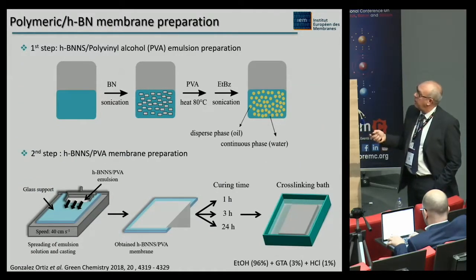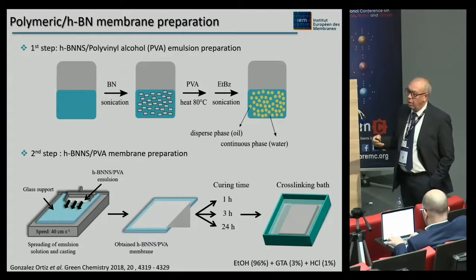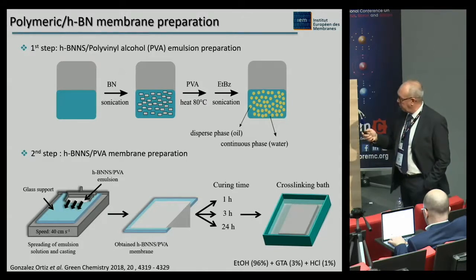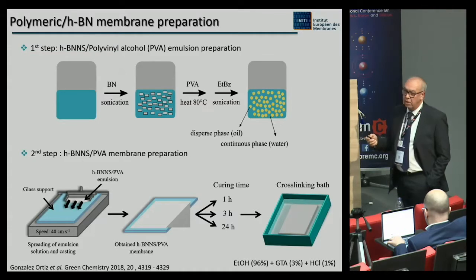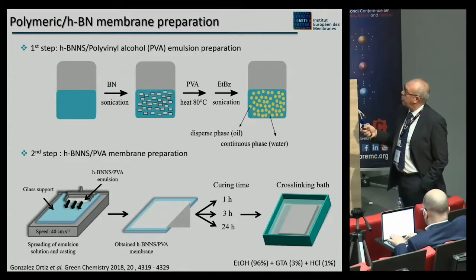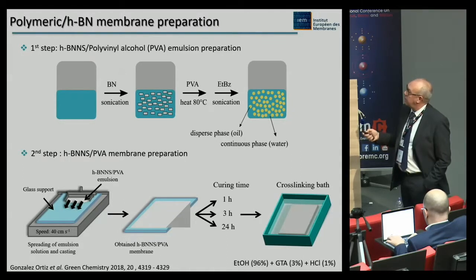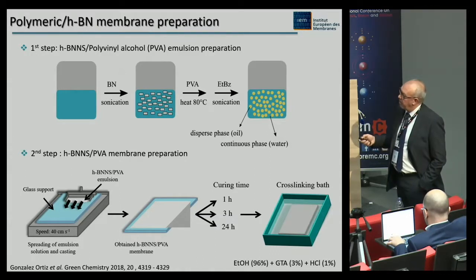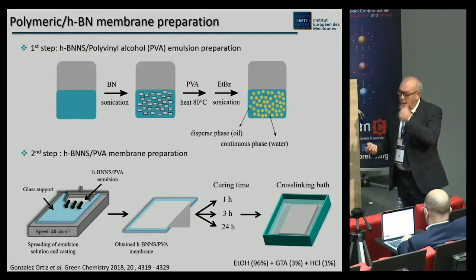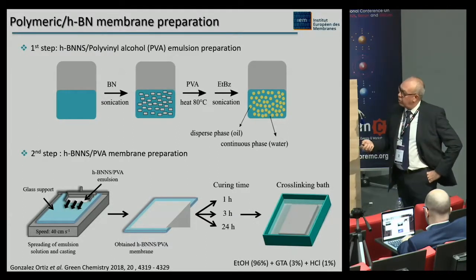So the technique is also relatively easy. The first step is the same. You put BN inside a water phase. You sonicate to exfoliate the sheets. After that, you add the polyvinyl alcohol. You heat that at 80 degrees. And at the end, the ethylbenzene with a last sonication, to obtain this kind of emulsion with, in that case, water as a continuous phase and oil as the dispersed phase. This emulsion can be used for membrane preparation with a technique very widespread for the preparation of polymer membranes.